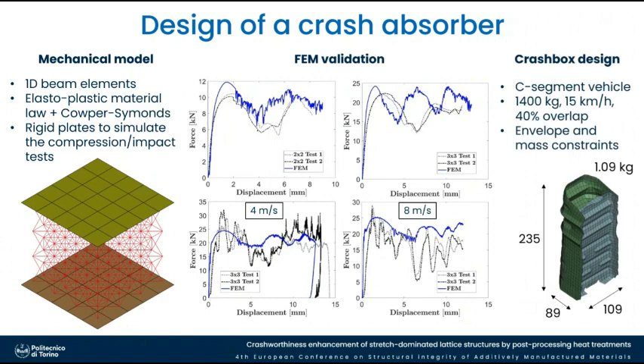So through that, we could afford the design of the crash box, the crash absorber, for an automotive application. We imagine to have a C-segment vehicle of 1,400 kilos that has to face an impact at 15 kilometers per hour. We imagine that all the energy of this impact must be absorbed by a single crash absorber. And we also retain the envelope and mass constraints. So we want our crash absorber to be smaller than the dimensions that are reported here, and the mass must be smaller than or equal to the mass that is reported here.